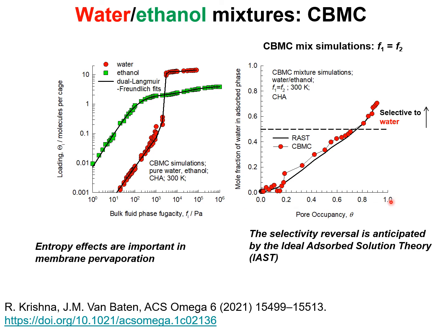At low pore occupancies, the mixture adsorption is in favor of ethanol that has the higher binding strength. However, for pore occupancies larger than about 0.8, the selectivity reverses in favor of water because the vacant adsorption sites within a cage are more easily filled with the smaller water molecules, and ethanol is entropically challenged in comparison with water.